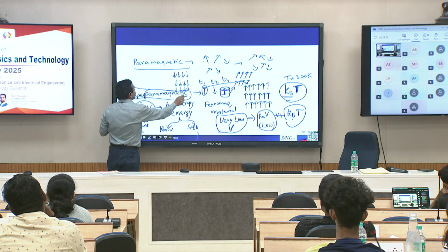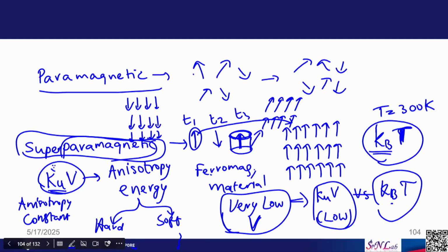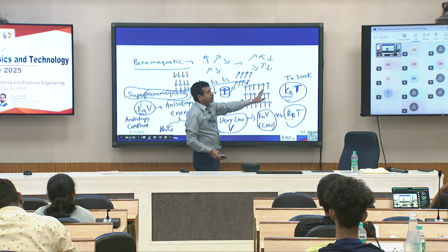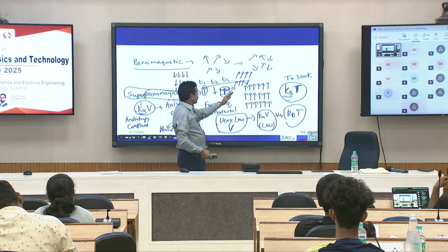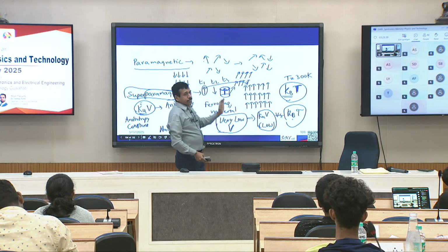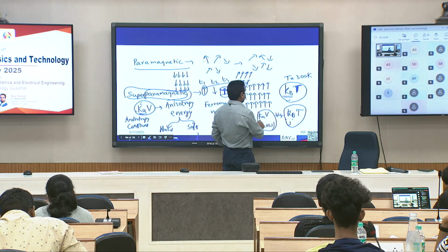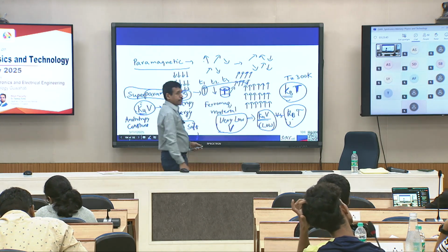The term paramagnetism basically refers to this time varying magnetic moment fluctuation. But here it is still a ferromagnet, because neighboring spins are parallel, but their magnetization fluctuates as a function of time due to this thermal energy competing with anisotropy energy.